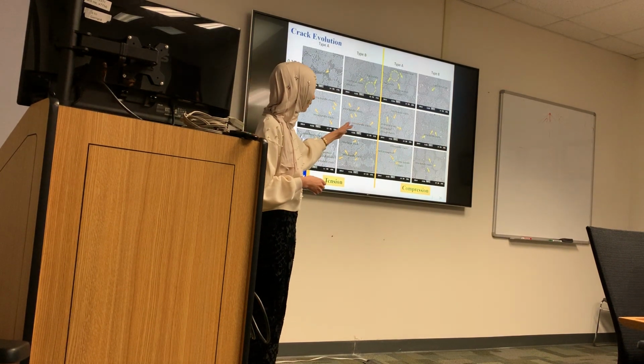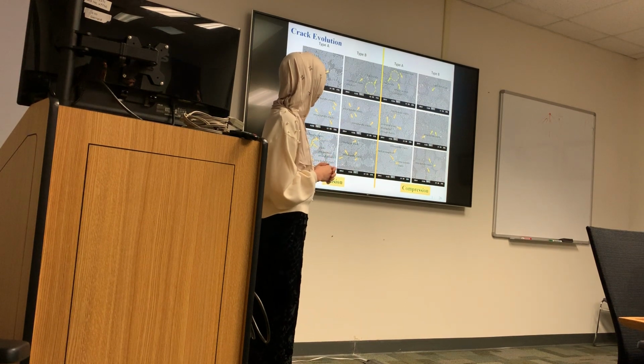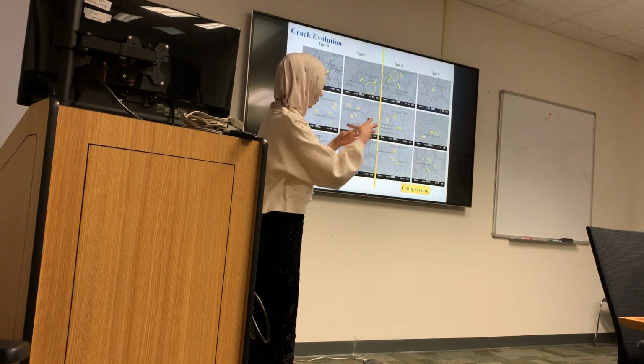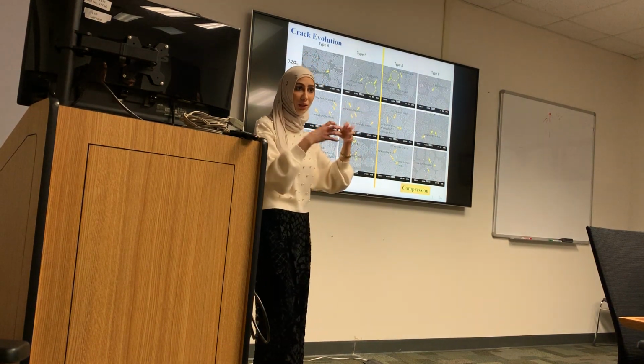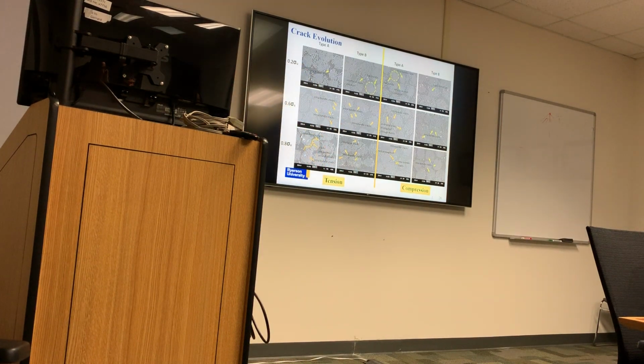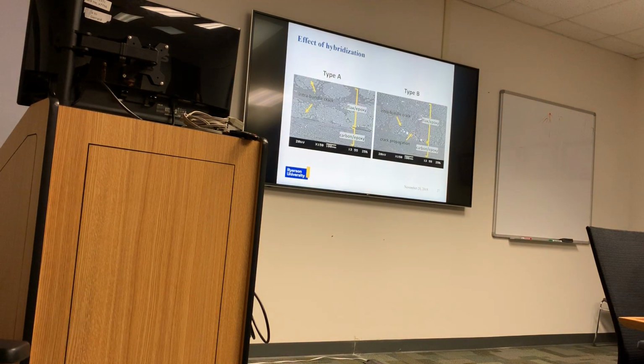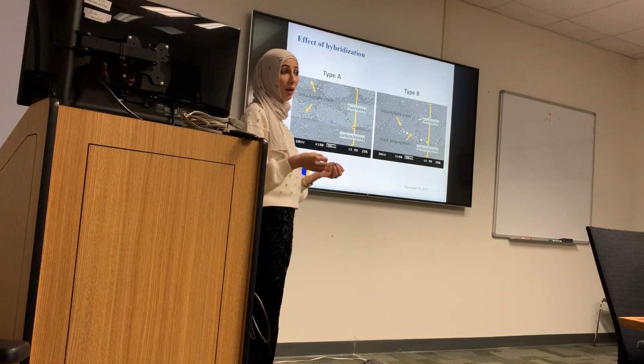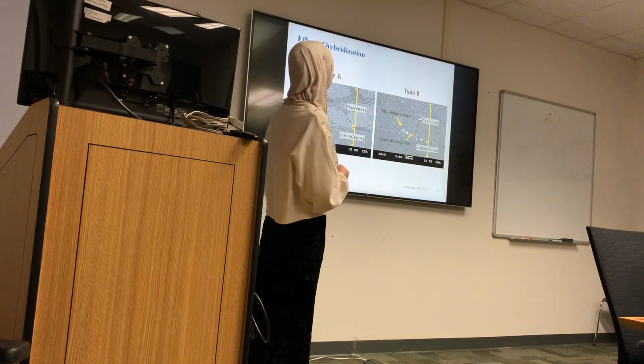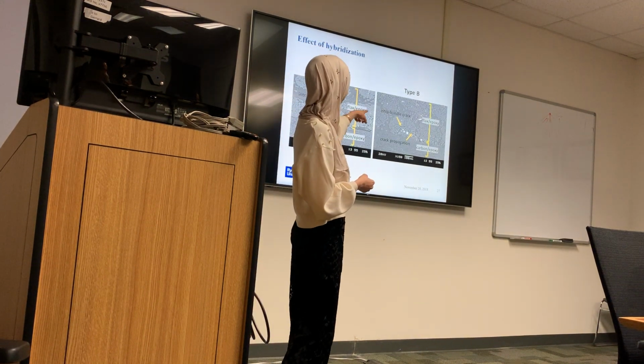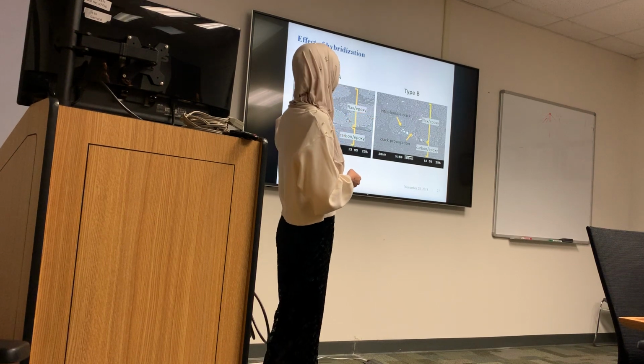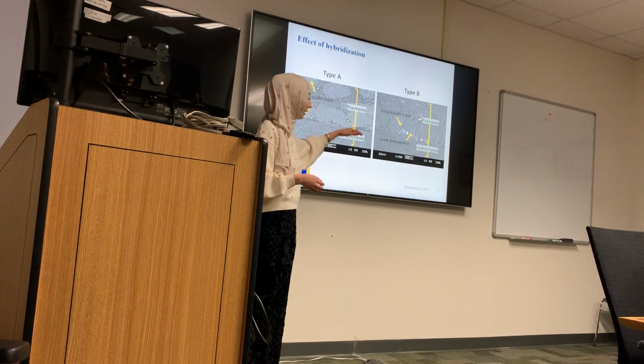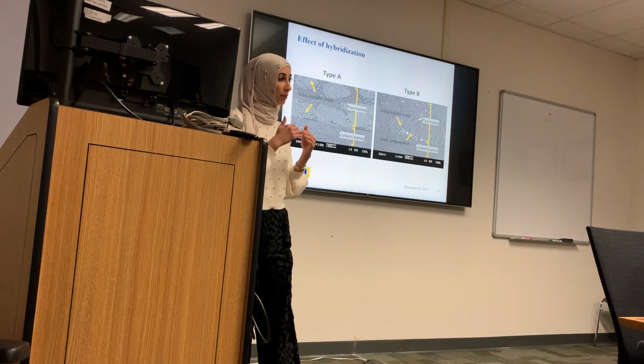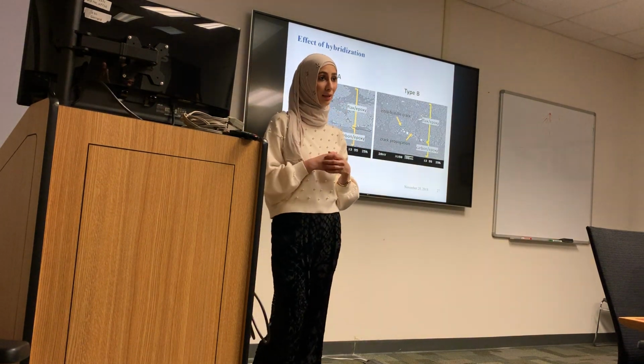We see here in the compression, it shows a different damage. We see most of the bundles are more accumulated, but that's because they buckle, and that's what we experience. We also wanted to see what is the role of the carbon fiber within this crack. You see here, when there is initiation of a crack and propagation, the carbon fiber, which is the bottom one, works as a hinder and prevents the crack from propagating along this material.